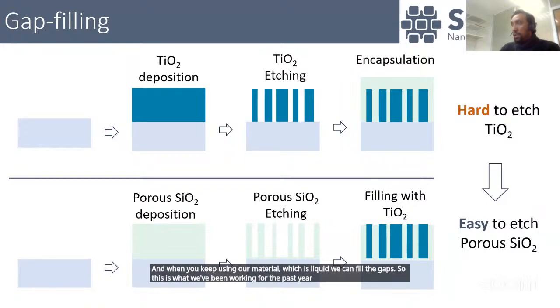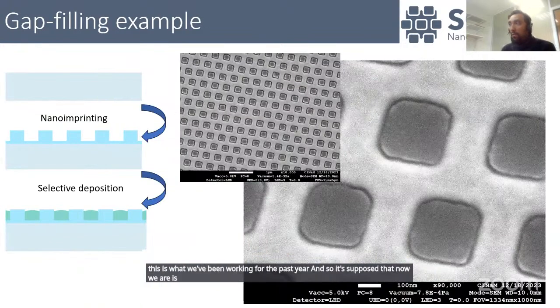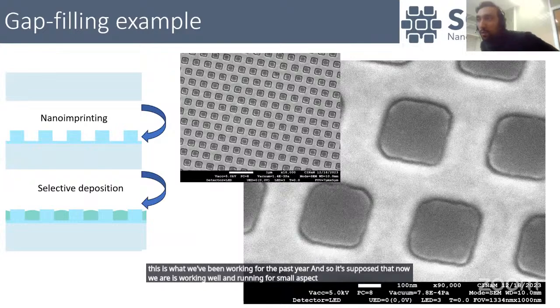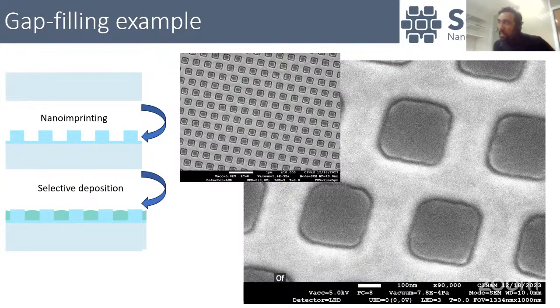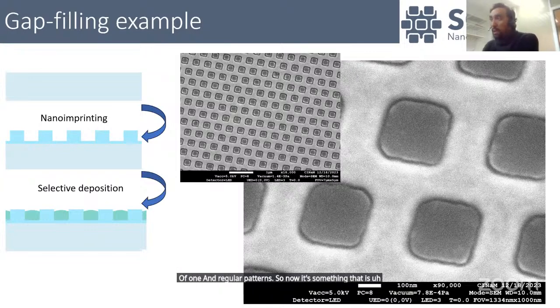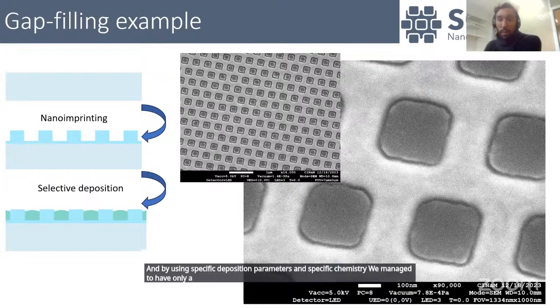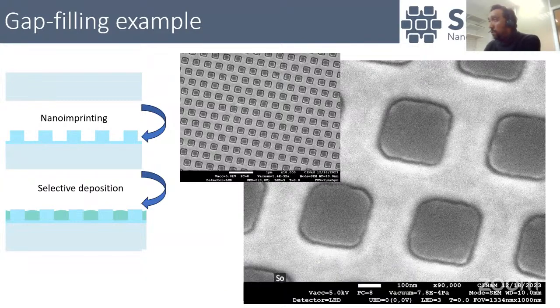It's a process that is now working well and running for small aspect ratio, with an aspect ratio of 1, and regular patterns. So it's something that is scalable to large area. Basically, we start with nano-imprinting a low refractive index material, and by using specific deposition parameters and specific chemistry, we managed to have a selective deposition only in the holes. Today it's very efficient and works quite well for standard, uniform patterns. And now we're in the process of developing this further for metasurfaces and more complex designs.